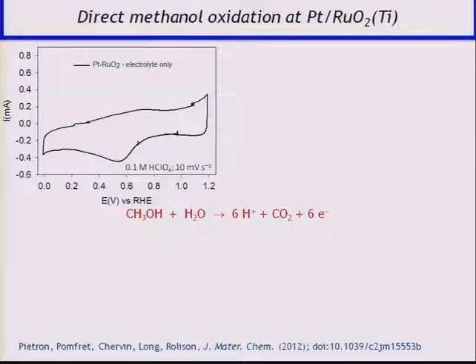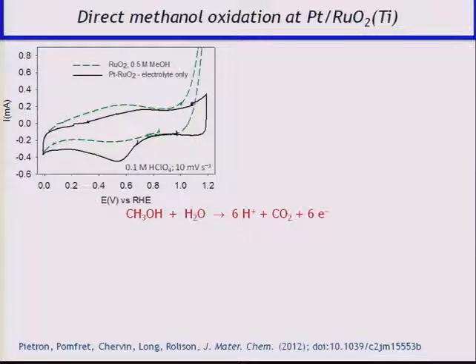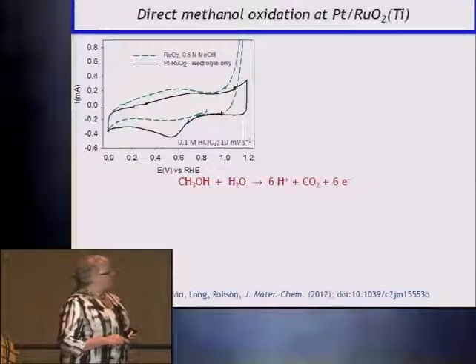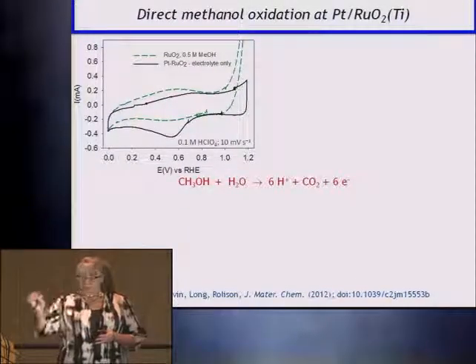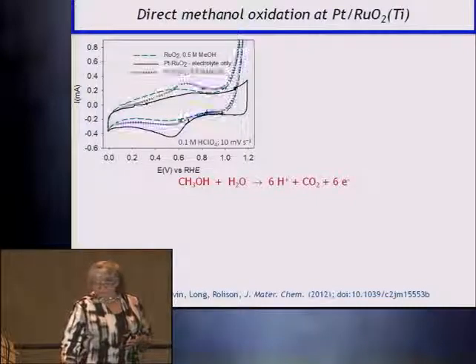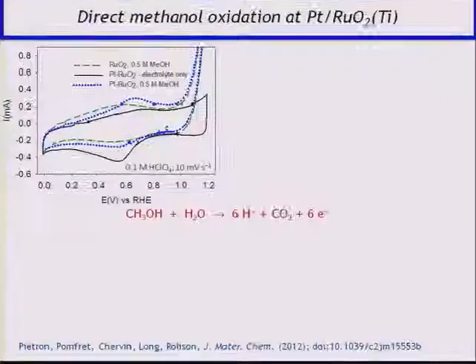Here's the curve you've already seen before: nanometric bits of platinum dispersed on the nanoskin of ruthenia supported on titanium. With just the ruthenia and methanol, there's mostly capacitance, and then the ruthenia can do some oxidation of methanol, but you have to go to extreme oxidizing potentials. With the platinum, it doesn't change all that much, but it does change.